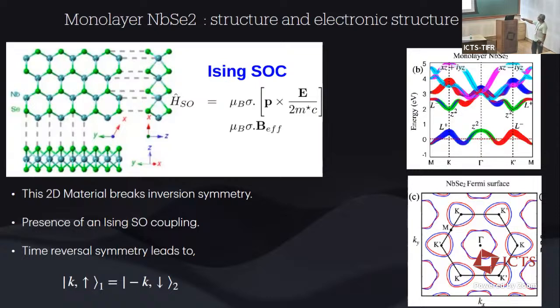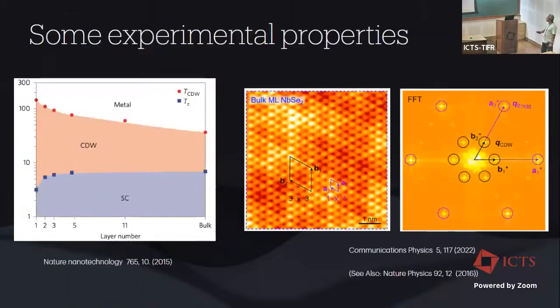And additionally, if you now include the effect of spin orbit coupling, you see that the pockets created by the single band split up into these red and blue pockets out here. You can think of the red pocket corresponding to a spin up state and the blue pocket corresponding to the spin down state because of the spin momentum locking. The way the Kramers degeneracy works is that for a point k, let's say out here, with a spin up, at minus k at the point out here, it is a spin down, right? So that is your Ising spin orbit coupling playing out in the momentum space. Now, this is overall the basic idea of what's going on in the structure and electronic structure of this material.